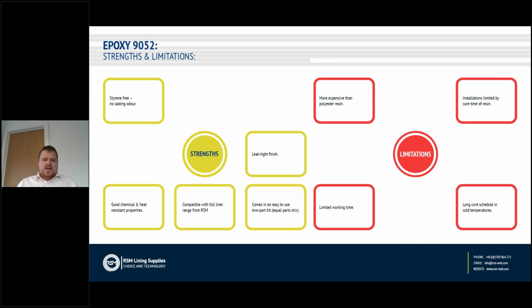To look at the sort of strengths and weaknesses or limitations of this product, as we say, particularly good for lining underneath properties or in-house applications. Good chemical resistance, up to around about 60 degrees. It's also compatible with our whole range of liners, and you get a leak tight finish.